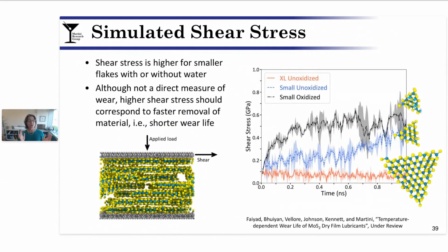However, it's possible there's no water at all. To evaluate this, we performed simulations as shown in the lower left, where we took these MoS2 debris or flakes and we sheared them. Shown on the right is a plot of shear stress as a function of time. The red data set is the largest triangular shaped flake, and the black and the blue are these smaller flakes. And what you can see is that with or without water, the shear stress is much higher, or they're less lubricious, for the smaller flakes. While this isn't directly a measure of wear life, it does suggest they are indeed less lubricious.